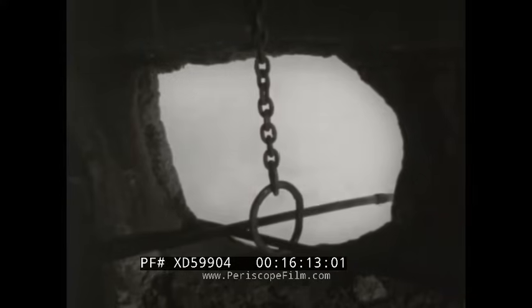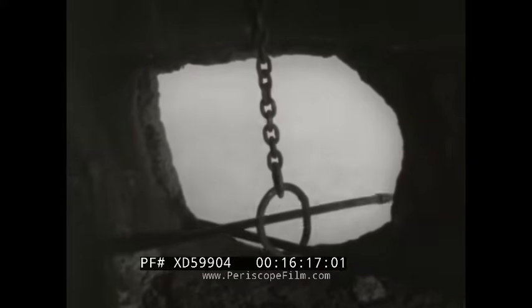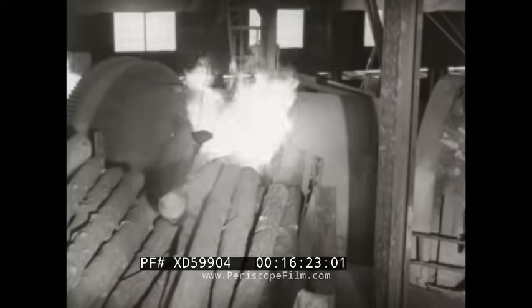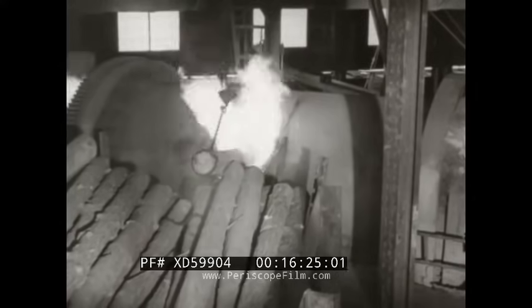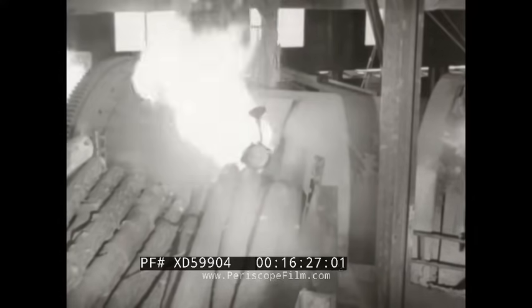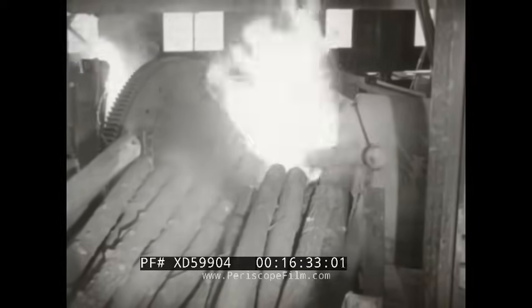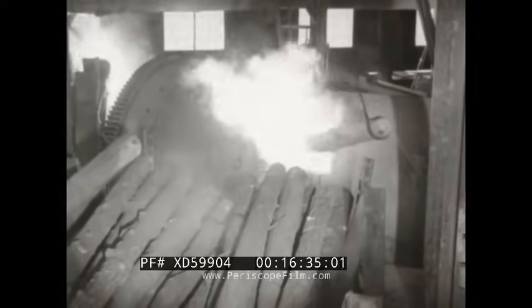The final impurities are removed by blowing air in excess through the molten copper. This accomplishes its purpose but introduces some unwanted oxygen. Green tree poles, therefore, are introduced into the molten copper. This represents an old discovery upon which modern science never has improved. The green wood carbonizes and the oxygen passes off, combined with the carbon, as a gas.